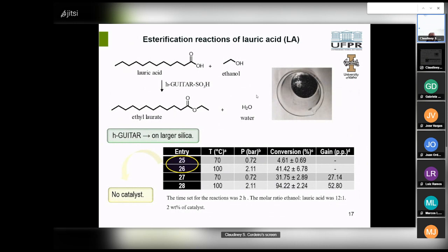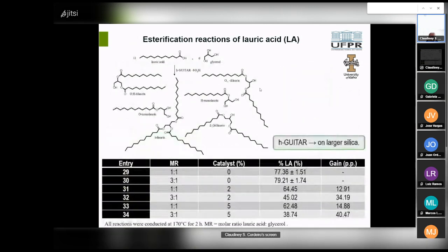In these experiments, we used guitar supported on larger silica. The results show that the solid catalyst is also active in ethyl esterification. These results demonstrate that the solid catalyst is active in the esterification reactions of lauric acid with glycerol, as shown in the table which displays the amount of unreacted lauric acid. This preliminary test showcased the potential use of the catalyst.